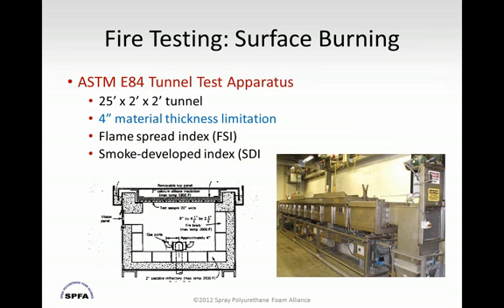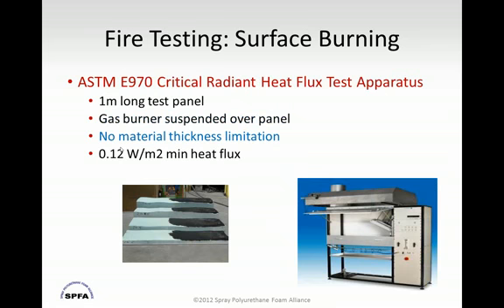To give you an idea, the ASTM E84 tunnel, if you haven't seen one, is 25 feet long and has a 2-foot by 2-foot cross-section. Here's a cross-sectional view. You see fire brick on 3 sides, and the material itself is suspended from the top. Here's an actual view of the 25-foot long chamber. At one end, we measure the exhaust. At the other end, we ignite the flame, and we watch that flame burn along the length of the chamber.